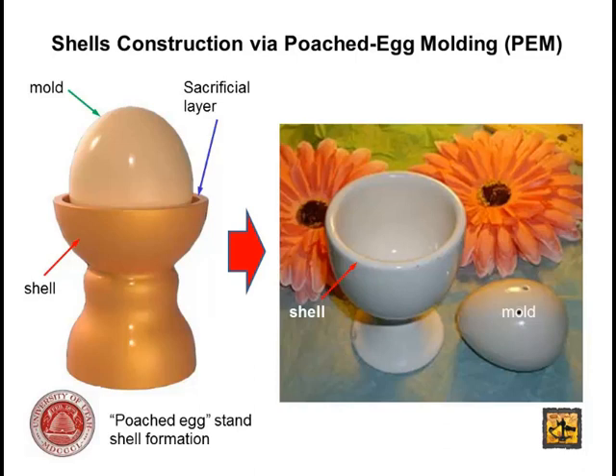So there's a space between the holder and the mold itself, which I can use for a sacrificial layer: put a material there and remove it later. On top of that, you have a structural material, and this whole thing is supported by some kind of post. So you can make a shell if you can somehow deposit these films on top of your mold and then remove the top, and then you flip the entire structure, and you end up with a shell only, and the mold you could reuse. So that's the whole idea.